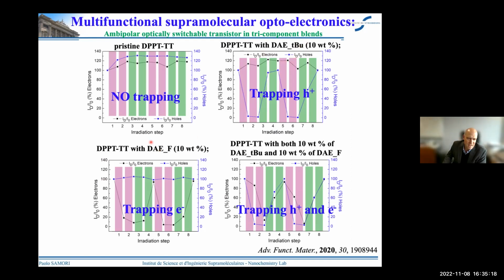If you do the other counter experiment with the fluorinated diarylethene, you will observe that we have a trapping and detrapping of the electron transport. And if you deposit and permeate through the organic semiconductor layer the blend of the two diarylethenes, you can see that upon illumination with UV light, we can trap both hole and electron transport. And then with visible light, we can recover both of them. So this is very interesting because we can have both different types of charges trapping and detrapping. This can be actually interesting for inverter applications.